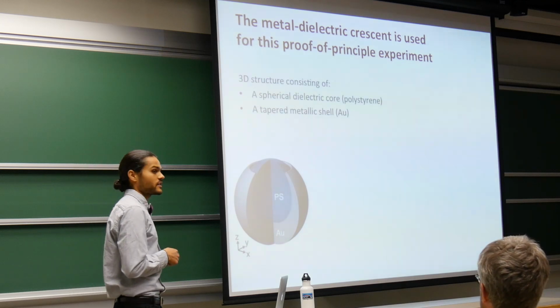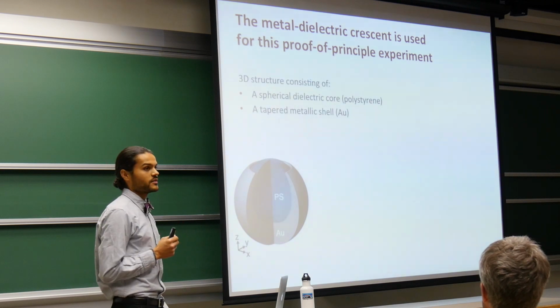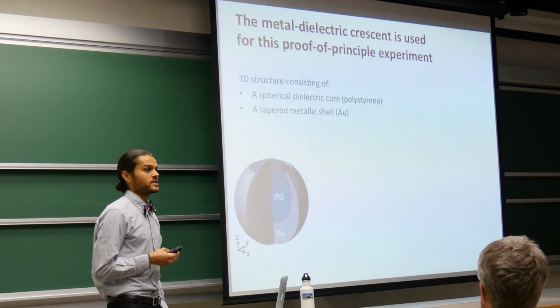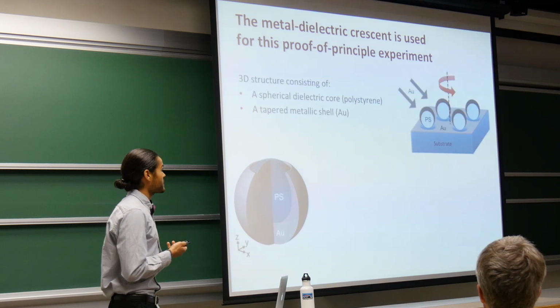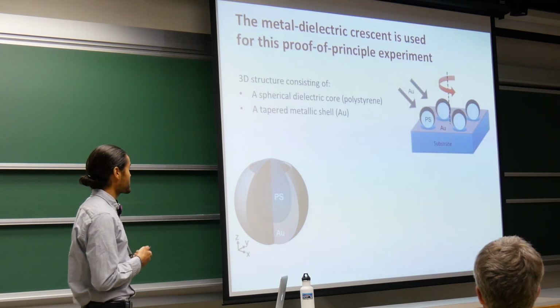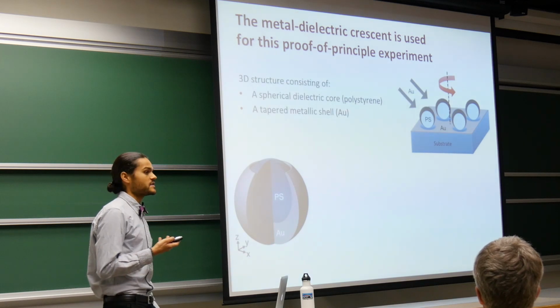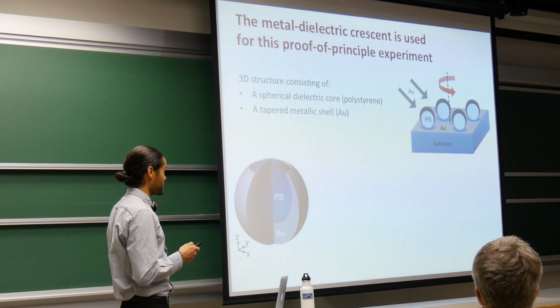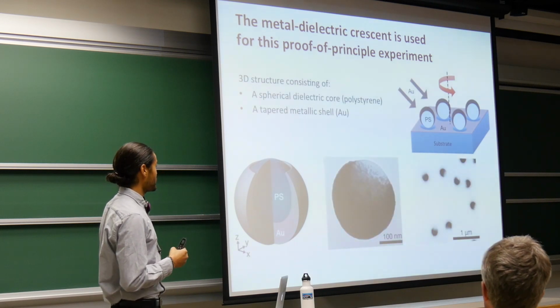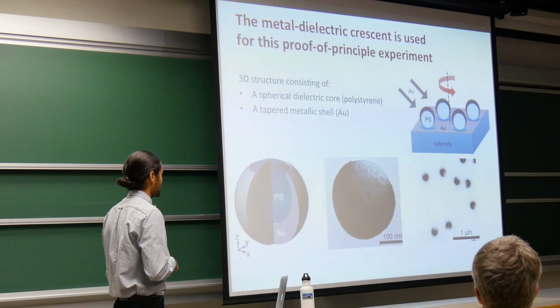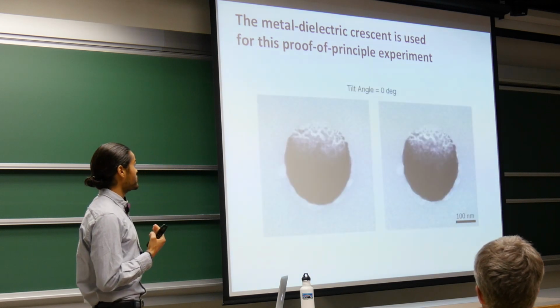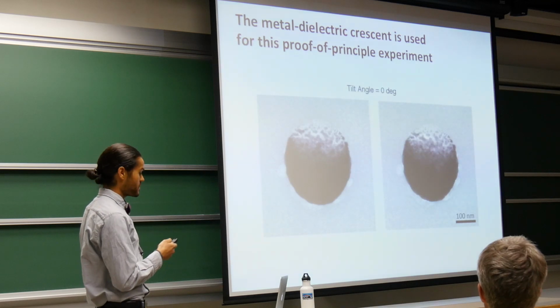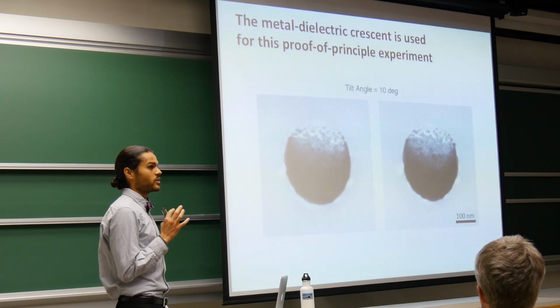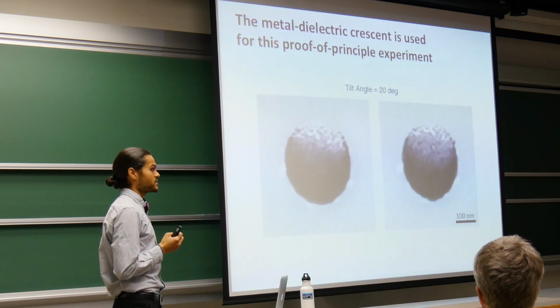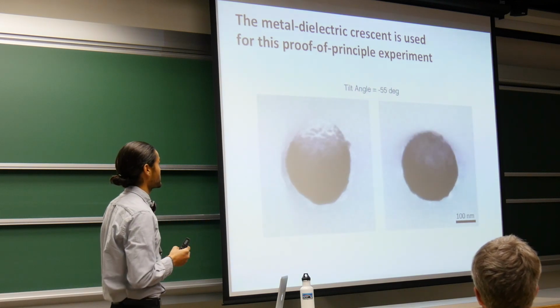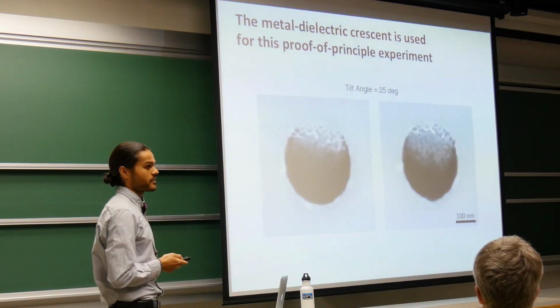But essentially, we have a dielectric core made out of polystyrene that's around 200 nanometers in diameter, coated asymmetrically with this gold shell. To make this, we simply disperse polystyrene beads on a substrate and then evaporate metal onto these beads while the sample is rotating at an angle. So this yields really nice uniform crescents that look a lot like our idealized cartoon. We can use a transmission electron microscope to better characterize their three-dimensional qualities, and by tilting the sample, we can see the really three-dimensional nature of this crescent structure. So here I'm creating a tilt series where I'm tilting in two orthogonal directions.